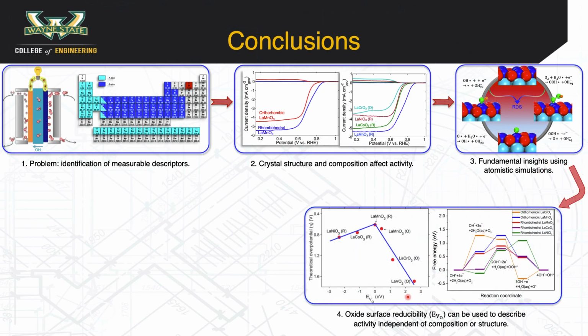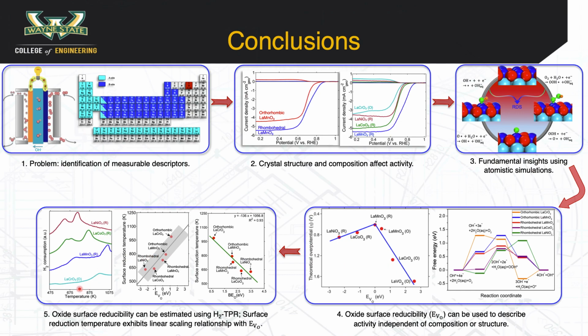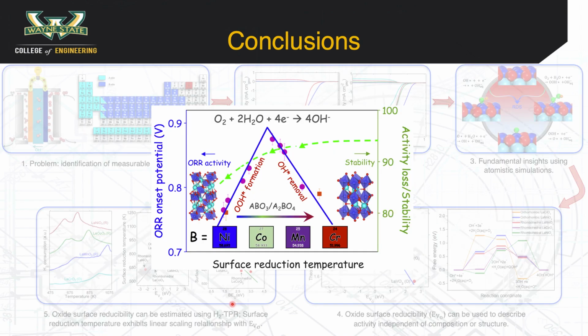These theoretical calculations suggested that the oxide surface reducibility, which is an inherent oxide property, can be used to describe the electrocatalytic activity of these oxides. The oxide surface reducibility was then estimated using H2 temperature programmed reduction, where the first peak was associated with the surface reduction. A linear scaling relationship between the experimentally measured surface reduction temperature and the theoretically calculated vacancy formation energy and the binding energy of oxygen was observed. All this was brought together in identifying surface reduction temperature, which is an empirically measured property, to describe the empirically measured electrocatalytic activity of these mixed metal oxides using oxygen reduction reaction as a probe reaction.